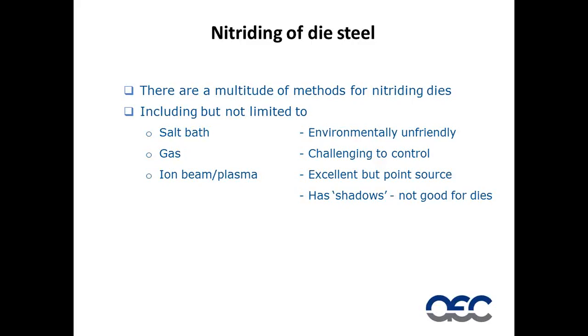This is an absolutely excellent way of nitriding steel. The unfortunate thing with this is it tends to act like a point source. So whereas gas nitriding comes from all surfaces, the ion beam nitriding tends to give us a problem where it creates shadows. So if you're nitriding a thin-walled flat die, you'll end up with a shadow on one side or the other. So although the quality of the nitriding where you get it is absolutely superb, you don't get it everywhere.